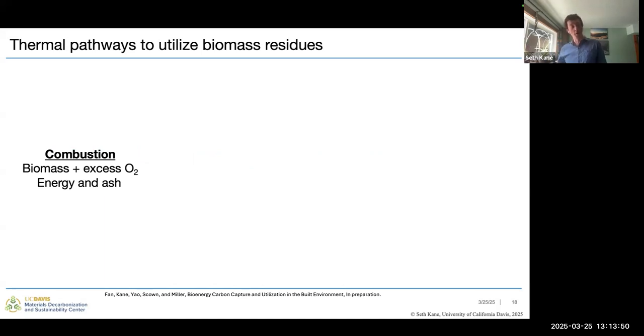So this is where we burn the biomass under excess oxygen, a process I'm sure we're all familiar with. And our primary products are going to be an energy product. And then that ash will vary a little bit depending on the ash composition of the original biomass. So as we saw earlier, if it's wood, there might be a little bit less ash. If it's a wheat straw, there might be a little bit more ash. And depending on the exact facility design, this can cause some issues during combustion of the biomass. If it is very high ash, it potentially can form some slag products that might be detrimental to running your process.